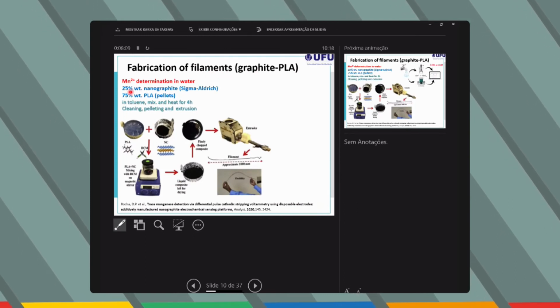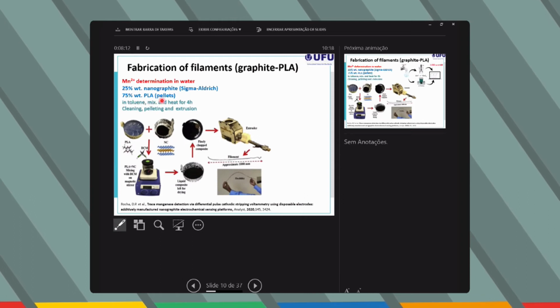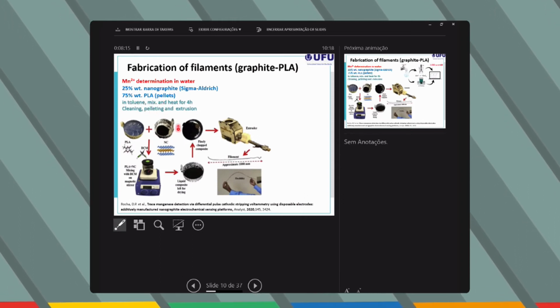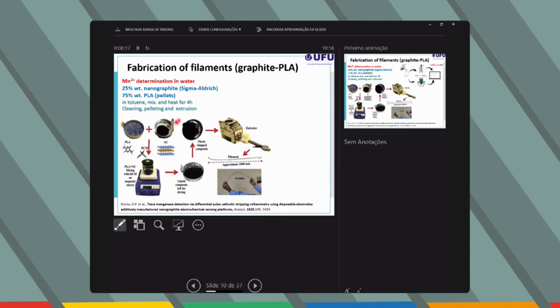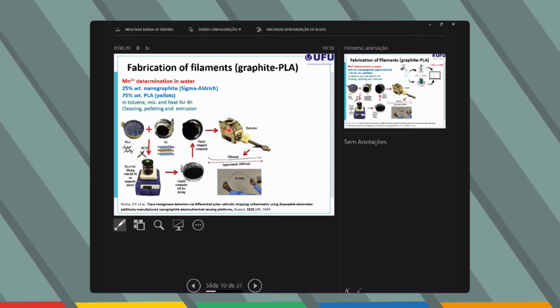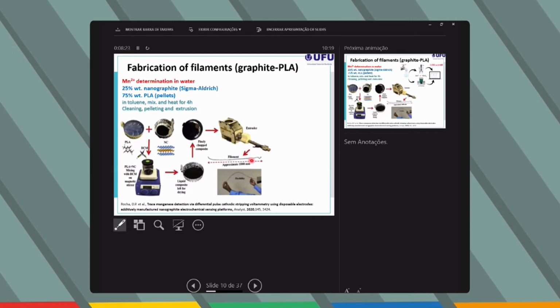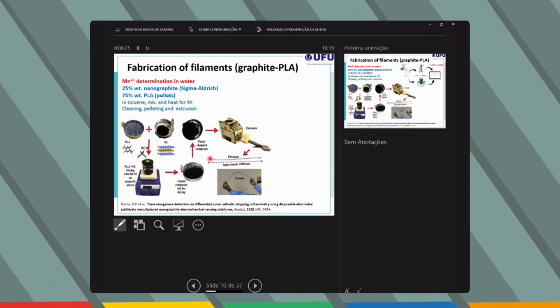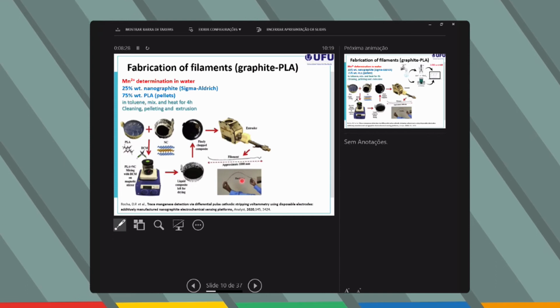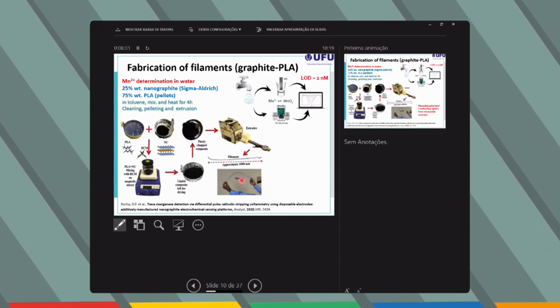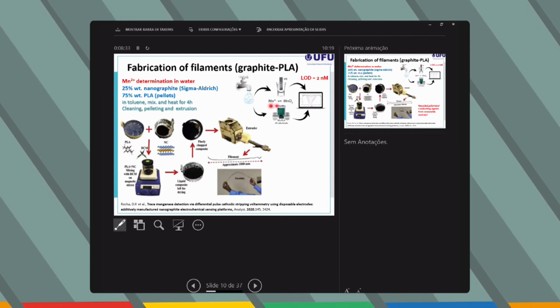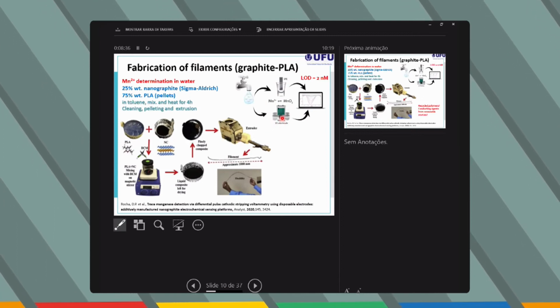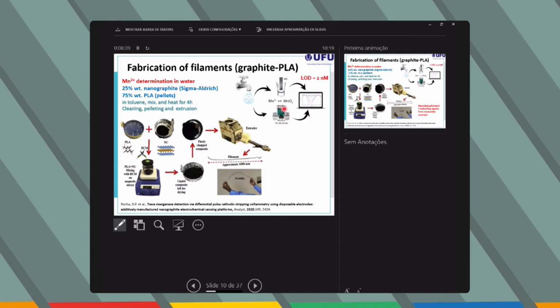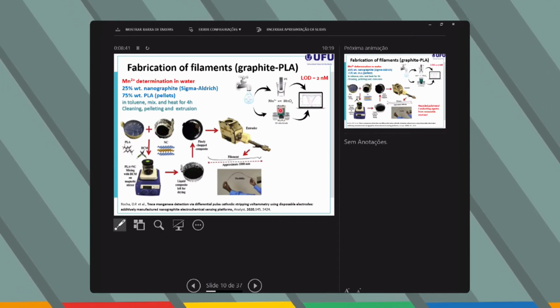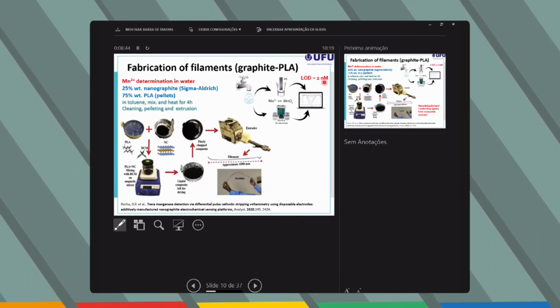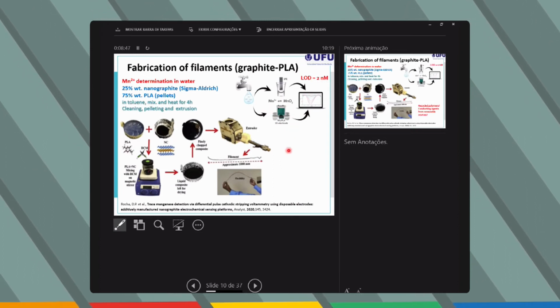Well, another possibility we're investigating in the group is the fabrication of our own filaments. The idea is to mix nanographites with PLA pellets, mixing, heating, and then to get this finally chopped composite, and then pass it through the extruder, and then we are able to obtain this flexible filament that can be used in the 3D printer. The idea was to produce a similar electrochemical device in which the conductive material is over here and the other two electrodes over here. And we demonstrate the possibility to detect very low amounts of manganese using this approach.